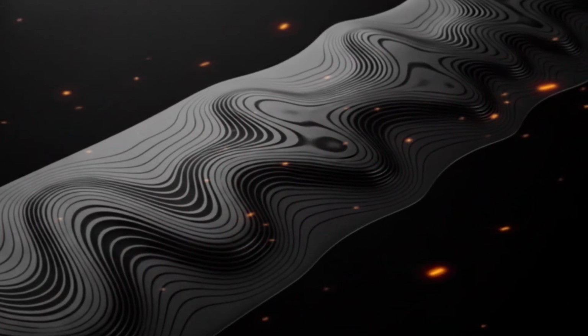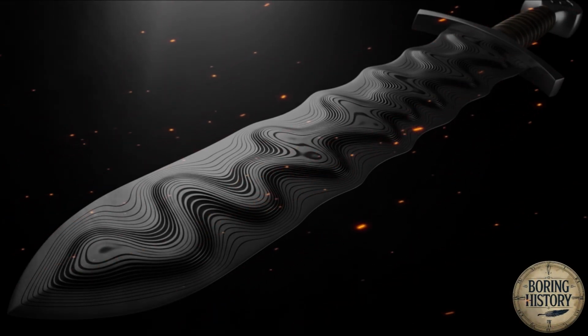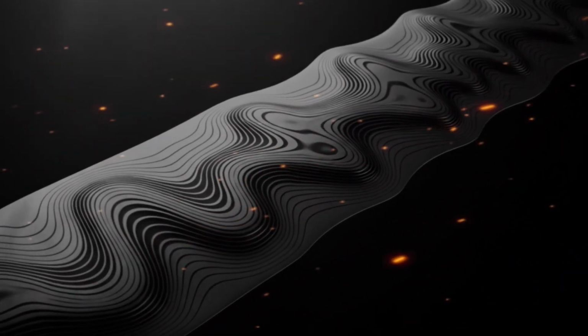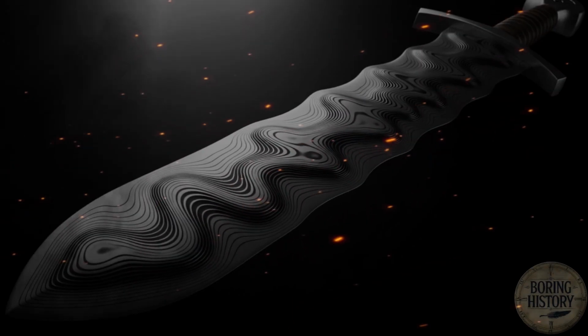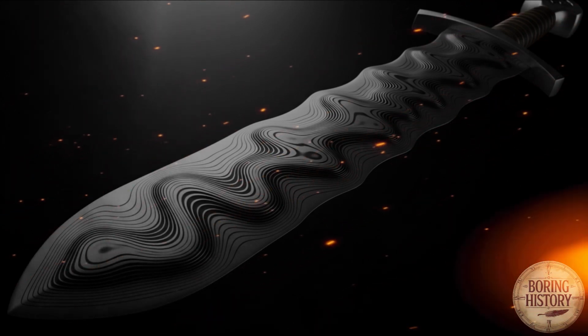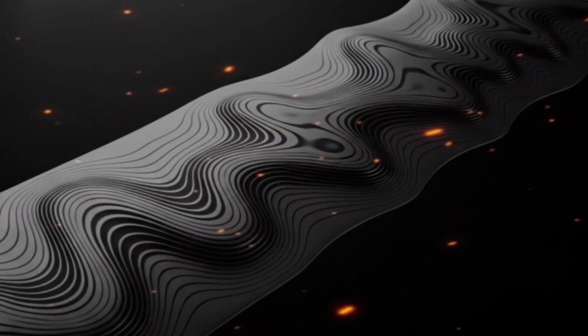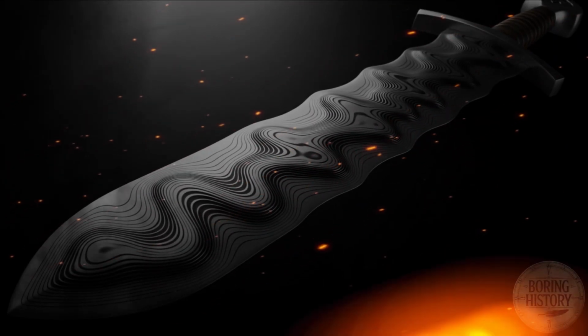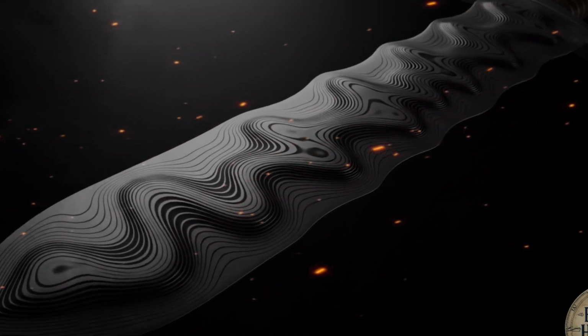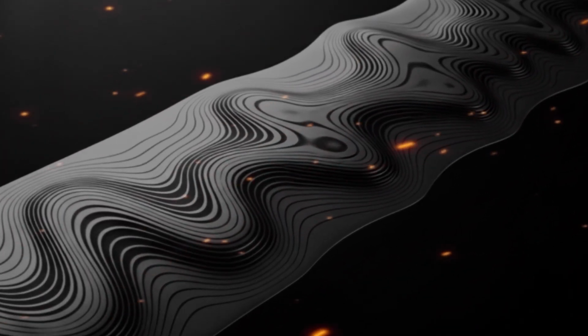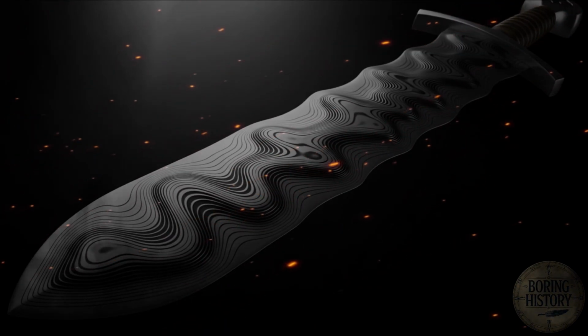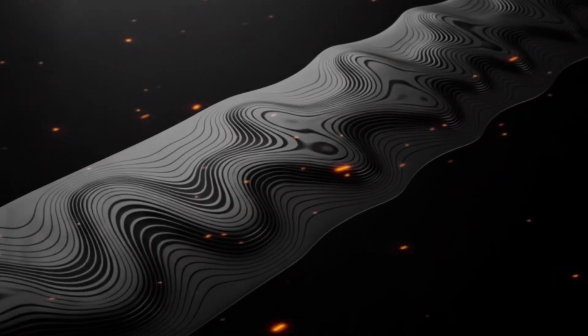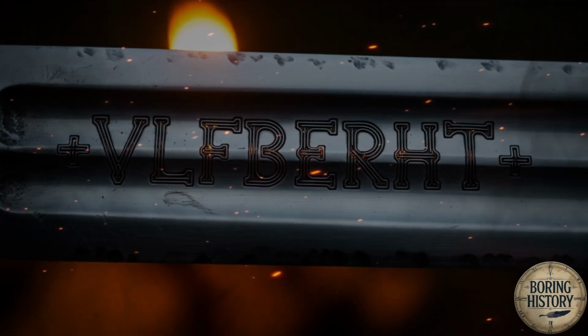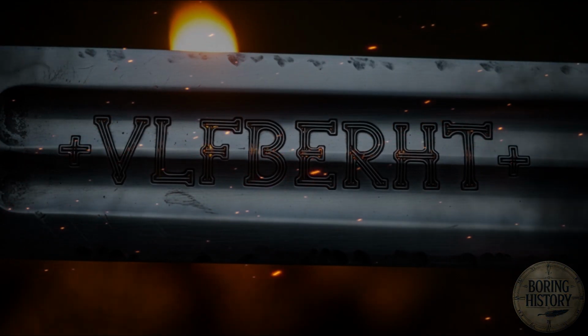When the steel is cooled rapidly, plunged into cold water or brine, dropping its temperature in seconds rather than hours, the carbon has no time to move. It is frozen in place, locked into the iron lattice in a strained, energetic configuration called martensite, and this configuration is very hard, harder than slowly cooled steel by a significant margin, hard enough to hold the edge that all those weeks of careful work had been building toward.